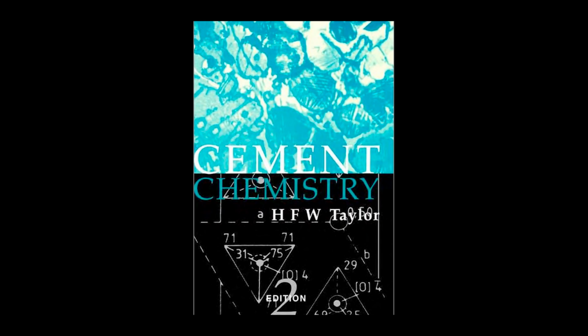We've traveled from the heat of the kiln, where MgO must be locked away by rapid quenching, all the way to the microscale dynamics of hydration, where CSH forms a semi-crystalline foil derived from tobermorite. And we discovered that the entire life of concrete hangs on crossing that critical percolation threshold, that 18% capillary porosity level, to cut off the pathways for decay.